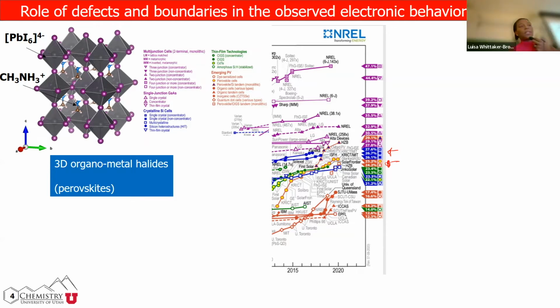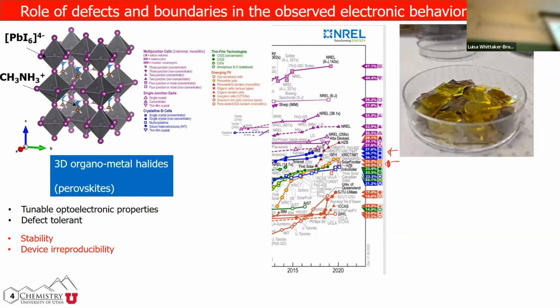The thing now with these materials is their device reproducibility and stability. If you actually look at them too hard, they will degrade in front of you, okay? And this is a very good representation of what is happening here. This Petri dish right here is samples that we have fabricated because we go to the synchrotron quite a bit, so we end up making a lot of triplicates of the same material over and over and over, right? All those films nominally have the same composition, yet they are degrading at different rates, right? So there has to be something triggering that decomposition in some films that is not triggering in the others, yet they're the same composition, okay?